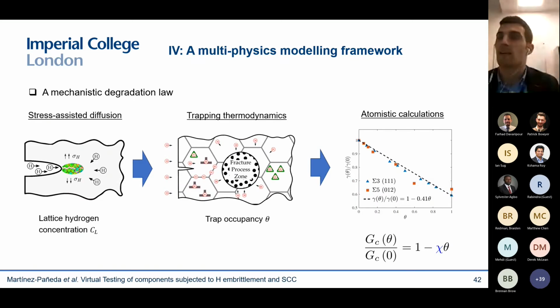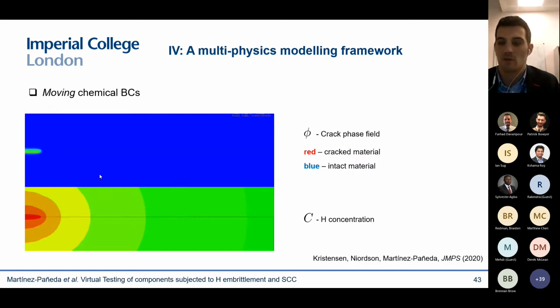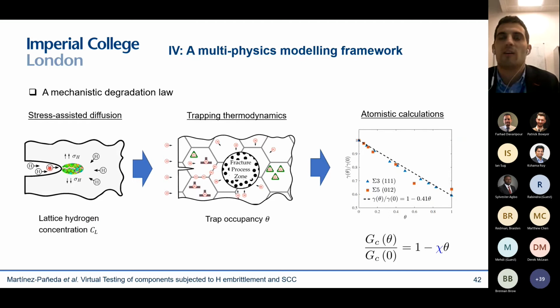What I do here, in order to provide this mechanistic understanding, is to connect with that third ingredient that I was showing you before. So I'm solving for the hydrogen concentration in the lattice, so I know exactly how much hydrogen I have. That tells me also, using these Oriani equilibrium equations, I know exactly how much hydrogen I have in my trap, in my critical trap, in those grain boundaries. And then I can go to these atomistic calculations, and these are done offline. I don't need to run an atomistic calculation, but that tells me quantitatively how much my fracture energy is going to be degraded. So the fracture energy of my phase field evolution equation is going to depend on the hydrogen coverage, which comes naturally from the simulation, and then on this hydrogen damage coefficient, which is something that you get from the atomistics. In this case, for nickel, it is equal to 0.41. So no fitting whatsoever, no bells, no whistles. Everything is dependent on, as a natural outcome of the simulation.